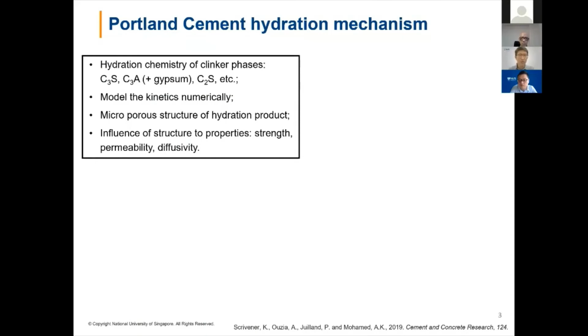Portland cement is the most widely used cement nowadays in construction practice. It's mainly composed of clinker phases such as C3S, C3A, and C2S. Right now, we are not completely sure about the hydration mechanism of these phases when they mix with water. We're also looking for ways to numerically model the kinetics and the hydration rate of these phases in a precise way. We're also trying to understand more about how the porous microstructure of the hydration product develops, how it evolves with hydration time, and how it influences the macro-scale properties of our concrete, for example, strength, permeability, and diffusivity.